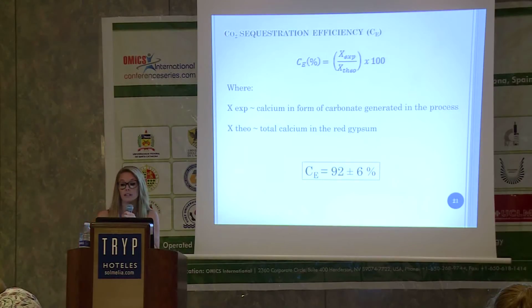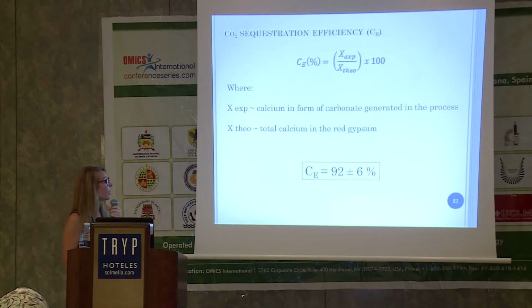In order to evaluate the degree of carbonation of these residues, the carbon dioxide sequestration efficiency was calculated. It is defined by the relation between the calcium in form of carbonate generated in the process and the total calcium in the red gypsum. The result shows that the red gypsum had a high degree of carbonation, and the uncertainty is very low, so the carbonation process with red gypsum is reproducible.